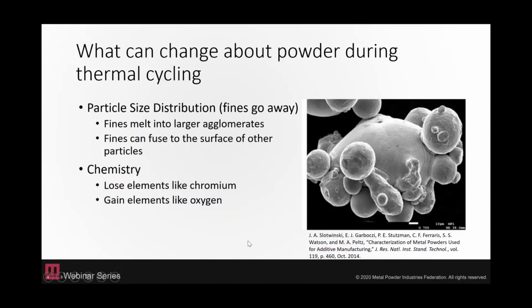So now that you know the differences between the two main metal AM processes, we'll talk about the sources of quality reduction. As you're building a part in the powder bed, you have the printed part and you have the surrounding powder. In electron beam, that surrounding powder actually gets partially sintered with each layer, and that helps the print properties, but that does change your powder. So when you recycle that powder, you're going to see a quality change due to that partial sintering.